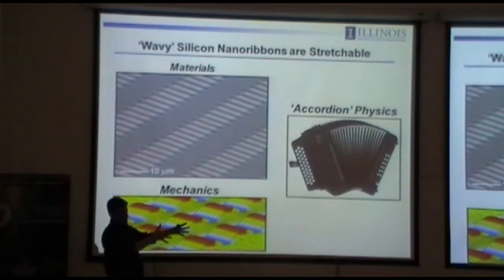Then you allow the silicone to relax, and what happens is it induces compressive stresses in the silicon that's mounted on the surface. And if those compressive stresses exceed a critical stress, what will happen is you will spontaneously induce a buckling instability that creates silicon in this kind of wavy geometry. So there's silicon ribbon 1, 2, and 3. There's the underlying rubber substrate. This is what it looks like when you allow that silicone rubber pre-strain to snap back to its original dimensions. You create wavy silicon. So it's a very hard material integrated with a very soft material, but generating a composite structure where the overall mechanics is dominated by the soft substrate, not by the silicon rigid material on top.